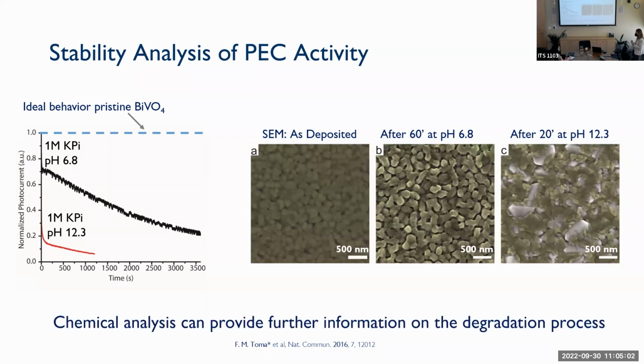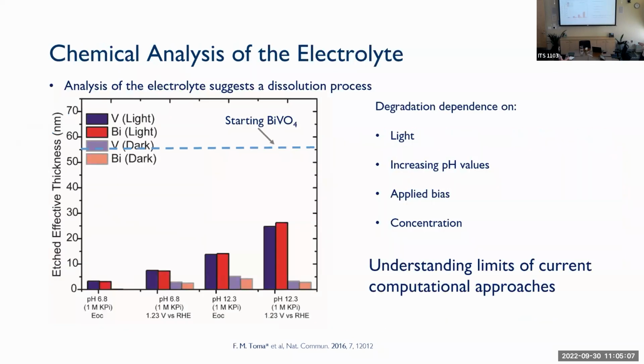So the chemical analysis can also provide you more information about the degradation process. And this is what we did. We took the electrolyte that was in the photoelectrochemical cell and we analyzed the contents of atoms or ions that were in the cell. So we looked specifically at vanadium and bismuth that are components of bismuth vanadate. And we looked at the content in the electrolyte to find out a few things here. This was done by ICP-MS, inductively coupled plasma mass spectrometry.